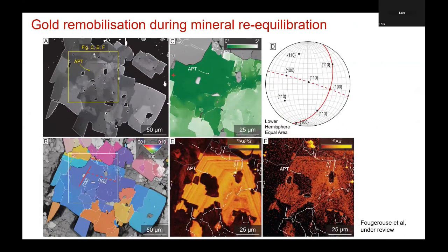All right, another case here. This one is a bit more complex, but pyrite especially, and gold-rich pyrite, arsenic and gold-rich pyrites, have this property sometimes of having these very funky textures. We have our nice oscillatory zoning like we saw before, and we explained what they were, but they also have these crazy corrosion gulfs, which don't have any arsenic and don't have any gold.